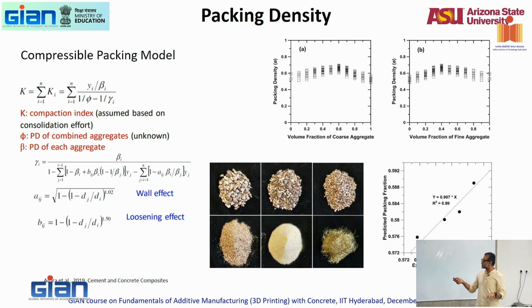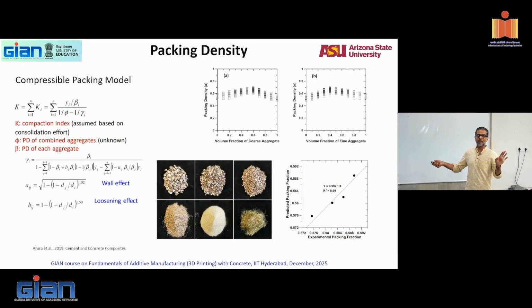Again, I'll eventually give you, I promise, in the next month, the software that will do all of this for you free. So you take the volume fraction of coarse aggregates and you start varying the fractions. This is about 800 simulations of so many different combinations. No experiments, simply your software will do it. And then I will do the theoretical packing density. You see, at about 0.6 volume fraction of coarse aggregate, I get my maximum packing density of aggregates. Maximum packing density of aggregates is about 0.72 or so, which means I can make a system with 28% paste. You see that? That's your minimum paste content to pack the system.